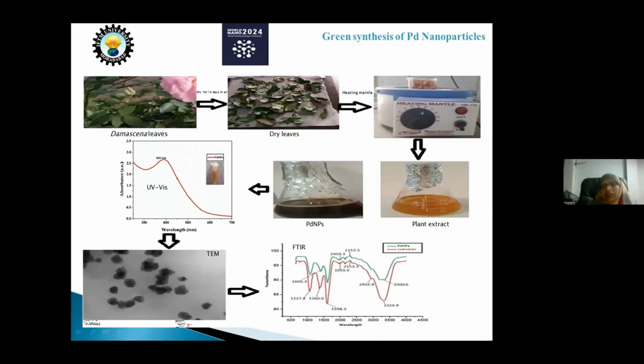After 15 minutes on a magnetic stirrer, I get palladium nanoparticles. This is the qualitative analysis, the change in color, which is due to nanoparticle properties. After the qualitative interpretation comes the quantitative interpretation, the UV-visible analysis at 360, which confirms that palladium nanoparticles have been synthesized.